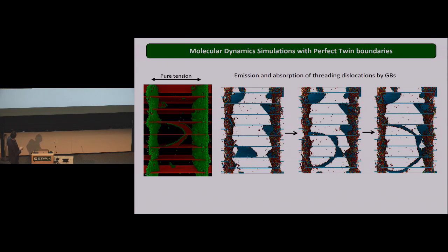I should also explain that these tiny dots represent individual atoms. The empty space there actually does not exist. In the visualization, we removed the face-centered cubic atoms so we can see the dislocations and the interfaces. So I'm only showing the defects in this simulation. But clearly, as I deform this system, I do not produce new dislocations. They just nucleate, travel, and disappear on the other side. No accumulation of dislocations. So that's the first conclusion, if you assume this interface to be perfect.